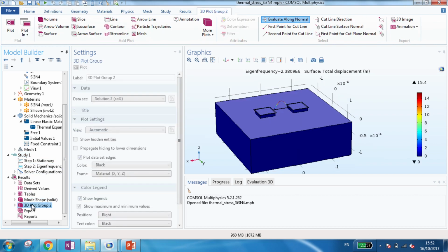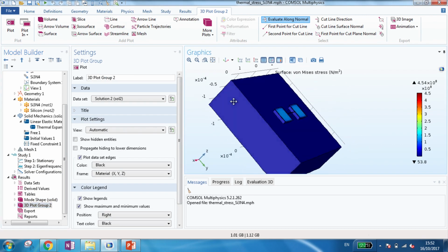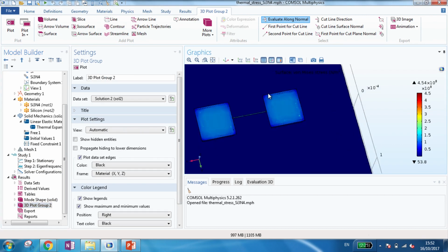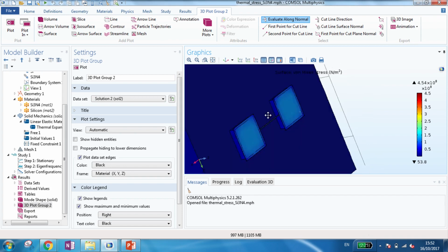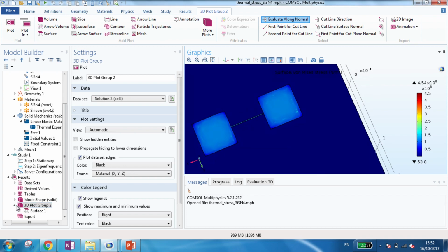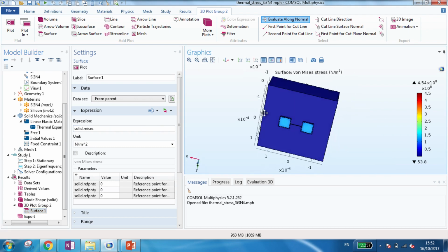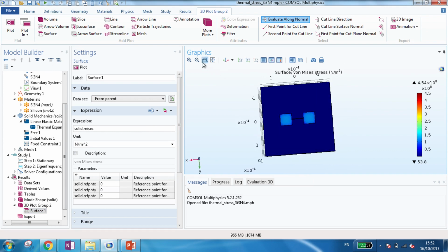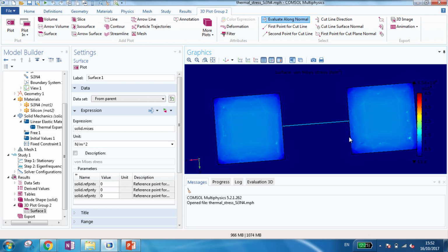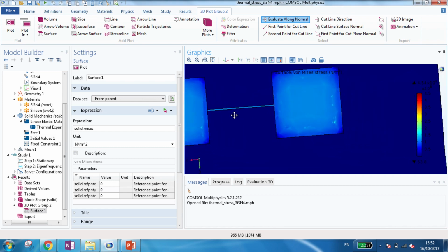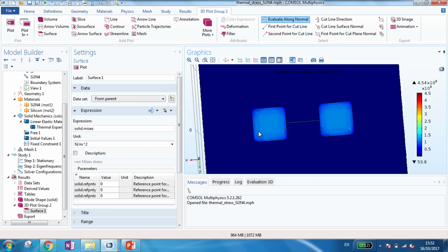you can get a stress of about 500 megapascal. So the stress with this technique, you can just read it off this plot, it's about 500 megapascal. And you might ask me where the rest of the stress comes from. My answer is I don't know. As far as I know, nobody knows exactly. We have some ideas, but I haven't seen any serious work that can calculate 1 gigapascal stress. So by that I conclude the session of today.